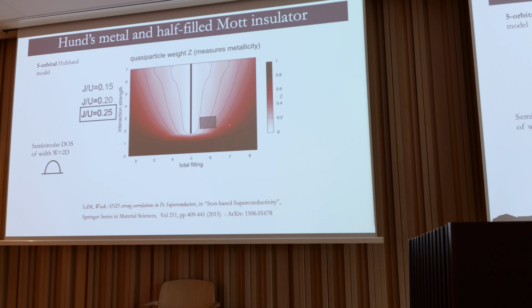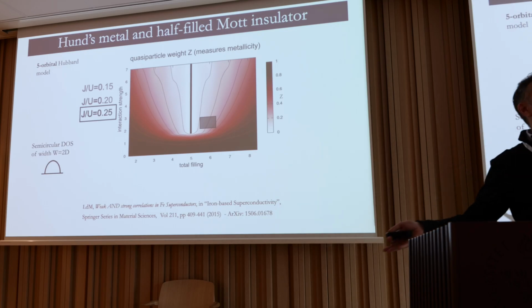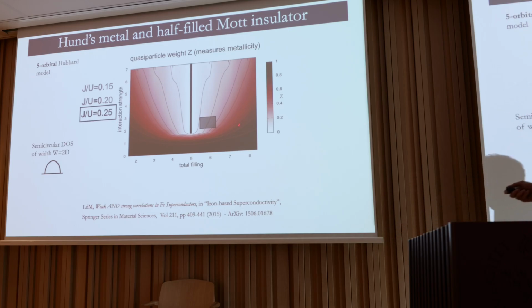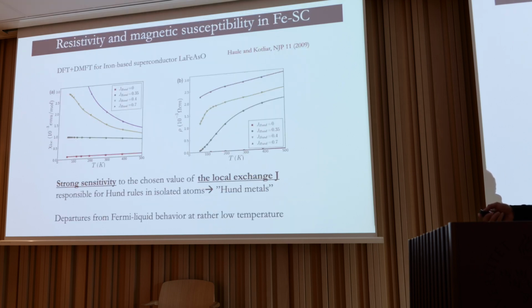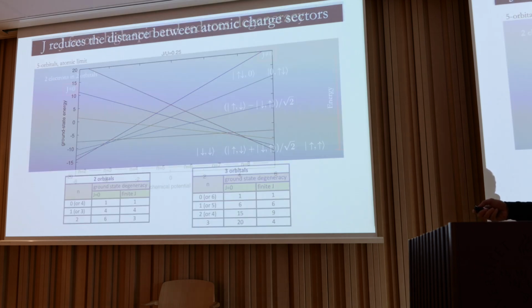So what I'm trying to argue is that what we see in this phenomenological picture, by looking at the Sommerfeld coefficient and the correlations in general of the 1-to-2 family, is that the dominant knob is the distance from half filling, where you would have a Mott insulator. That's the way I interpret this.